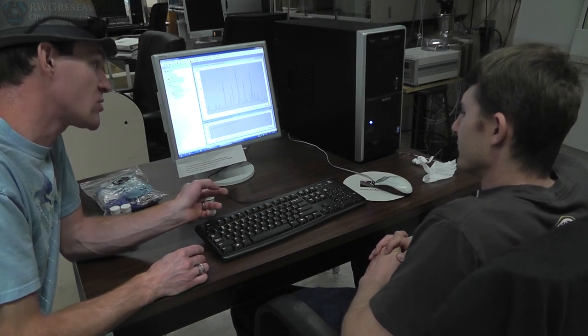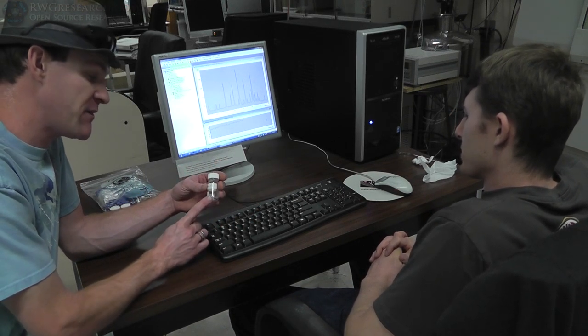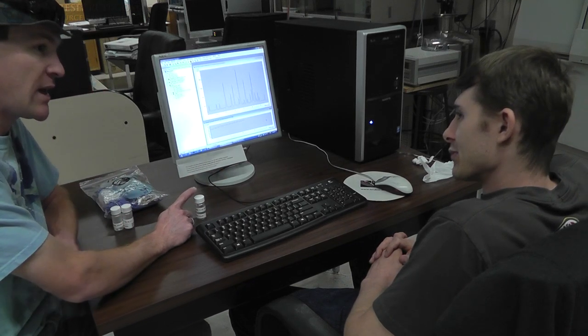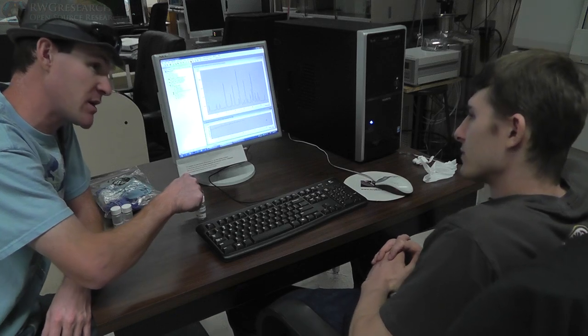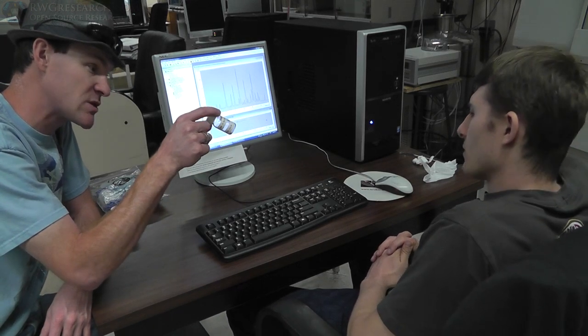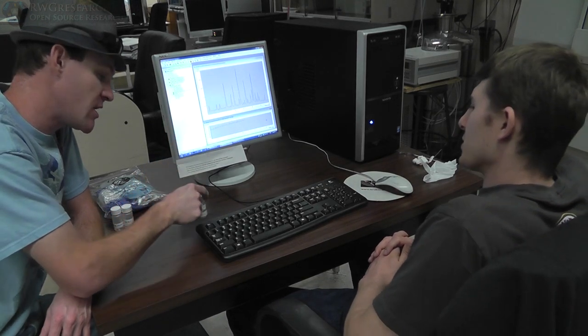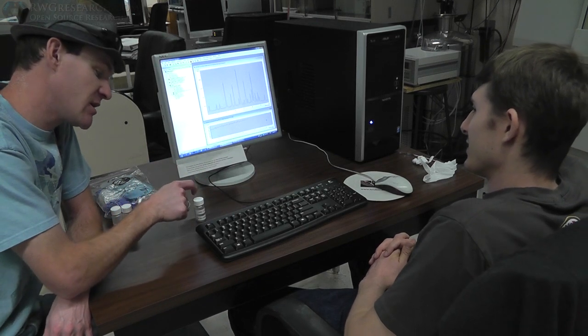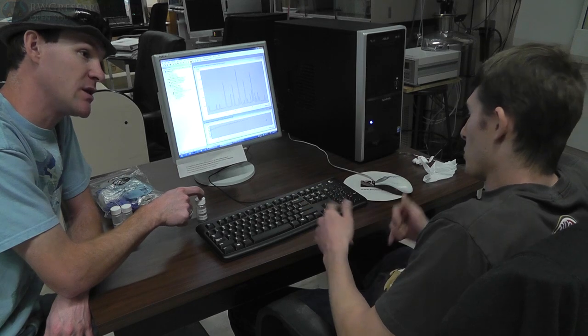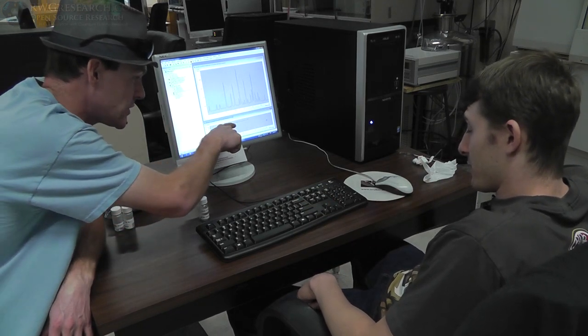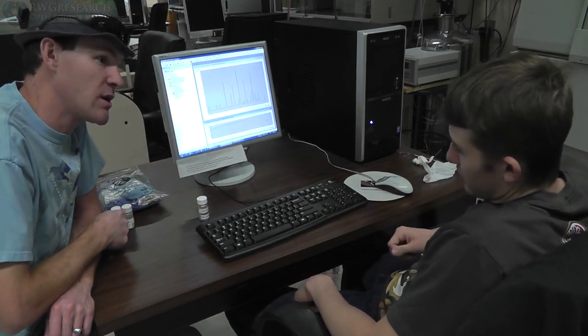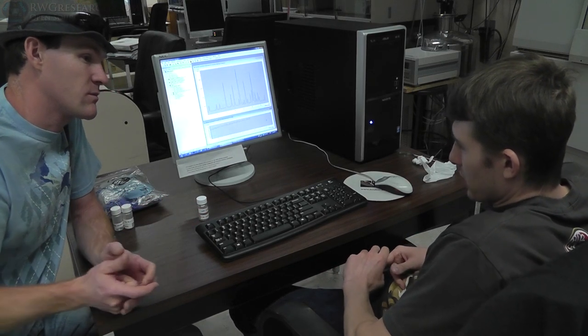But if the structure changed, it's because it's loaded with other stuff. Right. Here's the other thing. This sample versus a different one we had would be good to test against because this sample did not get calcined enough, which is why it's gray. I see. Another sample was calcined twice and it turned out white. Really? So this is not enough time to calcine complete. So that's the one we're running? Yeah. So maybe we've filled in all the pores with junk and now we don't see a structure? Is this true? I guess it'll depend on what we see here. So far we're seeing nothing. Yeah.